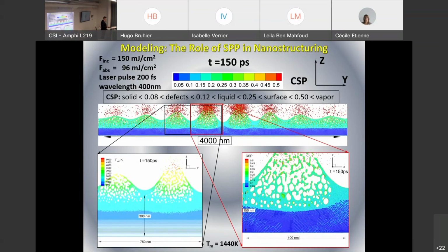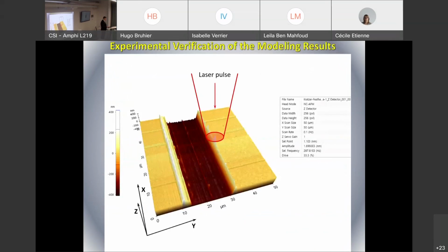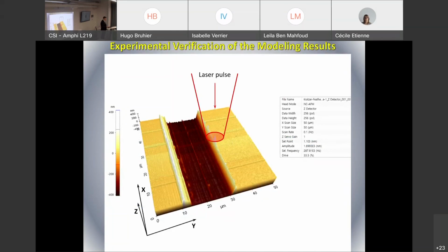That was quite successful this time. So now the fluence is lower, we have a gradual melting process, already noticeable modulation, and now the small structures growing in the same manner as was defined above as a mechanism of nanostructure growth, and eventually they solidify into quite nice structures with a fast decay, 5 periods, which exactly corresponds to the experimental measurements that were observed.